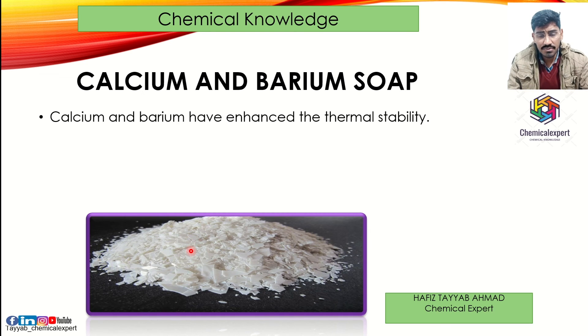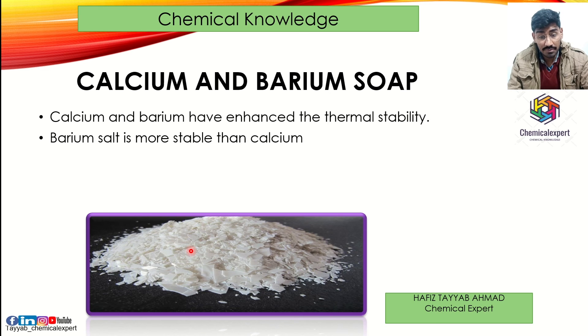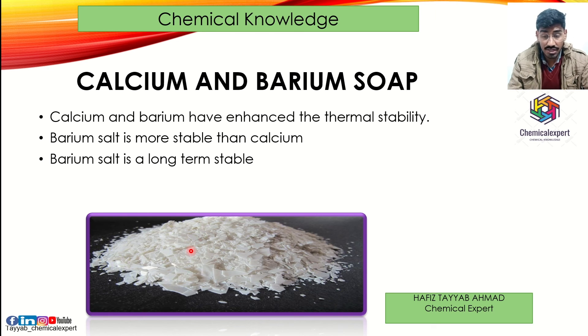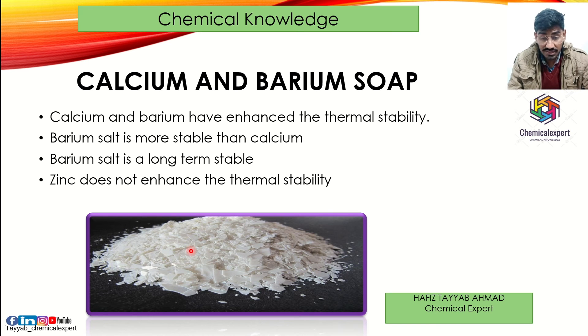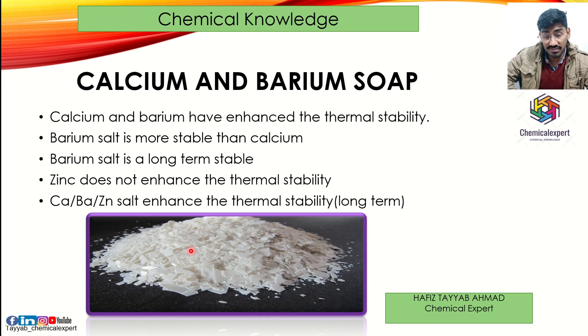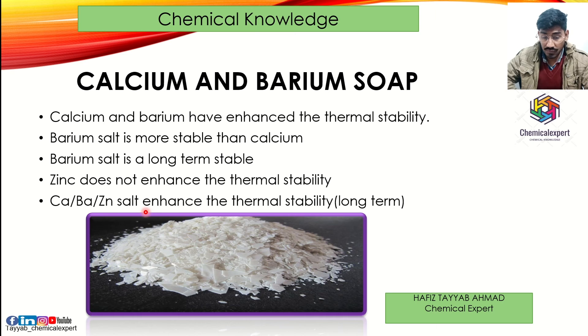Regarding calcium-barium-zinc salts: calcium and barium enhance thermal stability. Keep in mind that barium salt is more stable than calcium — barium salt provides long-term stability. Zinc does not enhance thermal stability; people may think zinc salt enhances thermal stability, but it does not. Zinc is only helpful for lubrication. Calcium-barium-zinc salt together enhance long-term thermal stability, and you can see this product comes in flake form.